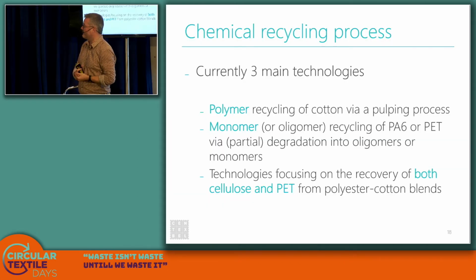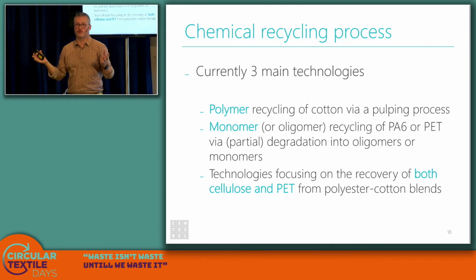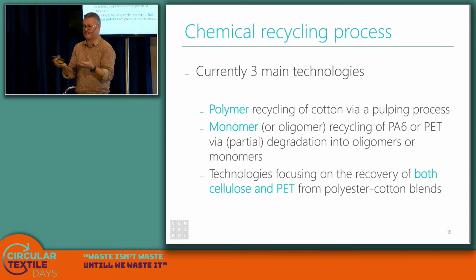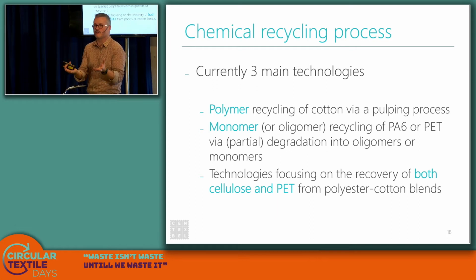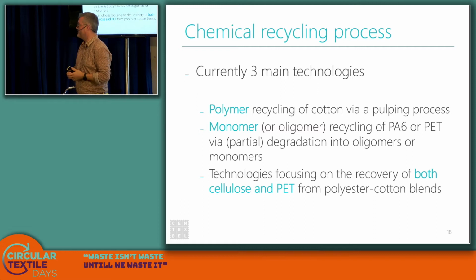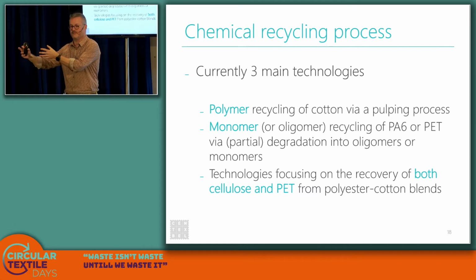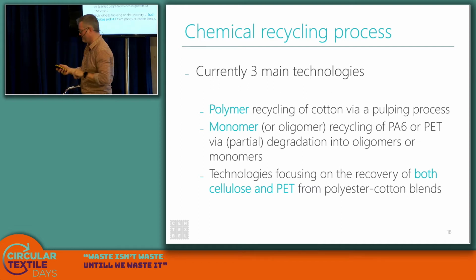Then chemical recycling, currently there are three main things that we see happening. That is actually the viscose process. So they use cellulosic material like cotton, flax, and so on to make a viscose fiber. So instead of wood, they make pulp out of the cotton, the viscose. They're focusing on cotton, but theoretically it would also be possible with other materials. Then you have the monomer recycling of polyamide 6 and PET. And then technologies that focus on both cellulose polyester blends, two fibers, where they want to regain both fibers. Because within the other technologies, you might dissolve the elastane and then it's gone with your solvent and you focus on one material. Here they are trying to recover two materials, so that's quite important.